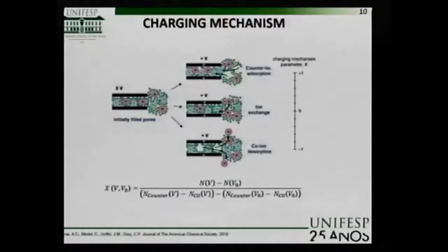The charging mechanism of a supercapacitor can be a counter-ion adsorption mechanism, in which the main process is the adsorption of the ions on the surface of the electrodes. It also can be an ion exchange mechanism, in which the main process is the swap between the ions inside the electrodes and the ions outside the electrodes.